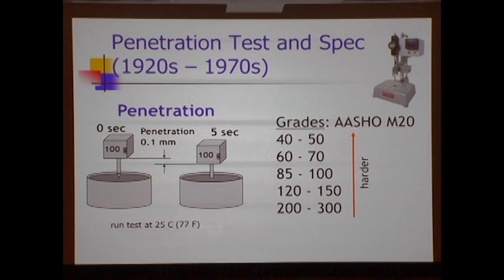And the American Association of State Highway Officials back then formalized this penetration grading system in a thing that was called AASHO M20. And we got different grades. In Texas, I obviously wasn't around when they were doing this, but I would suspect that there were two primary grades back then, probably 85-100 and 60-70 pen asphalt. The higher the number, the softer the asphalt.